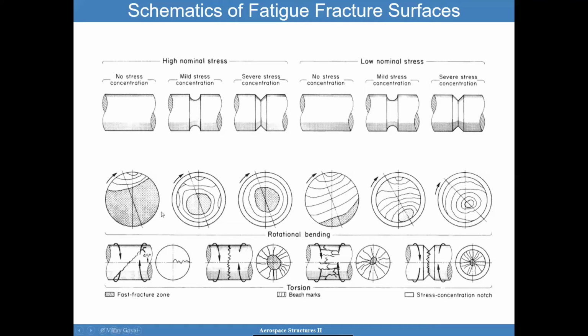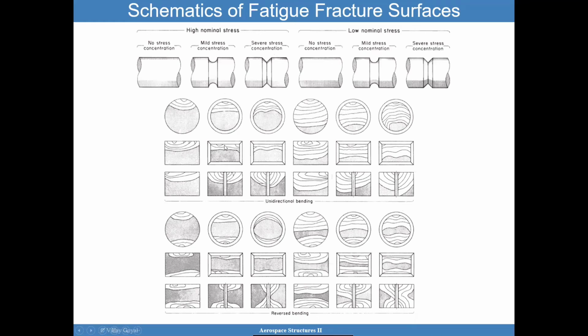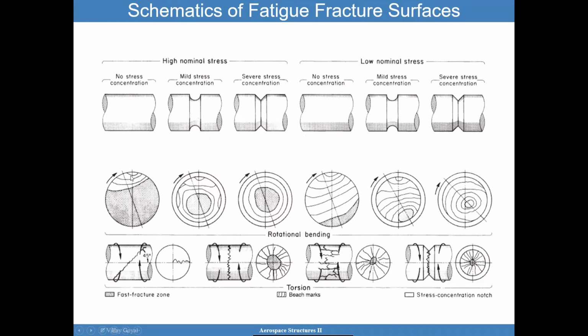When you have rotational and bending behavior in those situations, you're going to have less symmetric behavior of those beach marks, but in essence, it should follow this particular bending situation. But now with the rotational bending, you could start having this propagation in one particular side more than others. And then the final fracture will be towards the end center for stress concentrations that go all around. And here again, with almost no stress concentration, beach marks that look a lot like the ones we discussed here for pure bending. And then when you add the torsional component or rotational bending, you start getting these non-uniform beach marks with a final fracture towards the center, but the circles don't look all that uniform and centered compared to torsion alone.